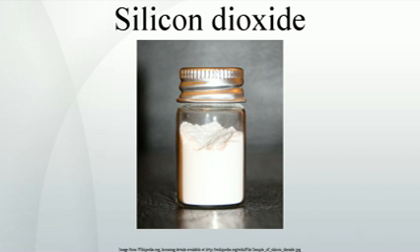Solubility in water. The solubility of silicon dioxide in water strongly depends on its crystalline form and is 3 to 4 times higher for silica than quartz. As a function of temperature, it peaks at about 340 °C. This property is used to grow single crystals of quartz in a hydrothermal process where natural quartz is dissolved in superheated water in a pressure vessel that is cooler at the top.